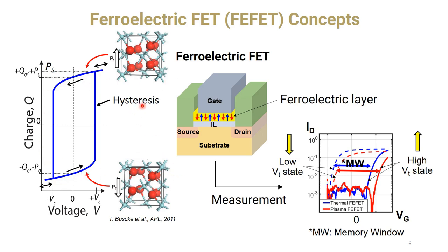So if we deposit this ferroelectric layer on the MOSFET structure and measure the ID-VG characteristics, we have two different results. First, if the polarization is down, it is called the low VT state, and we have this blue curve. And if it is the high VT state, with polarization up, then we have this other graph. So there is a difference depending on the polarization state. If we measure at 0 volts, the current is completely different. In the low VT state the current is high, and in the high VT state the current is low. So using this device, we can store data because we have two different states.